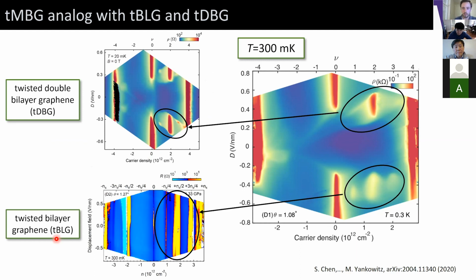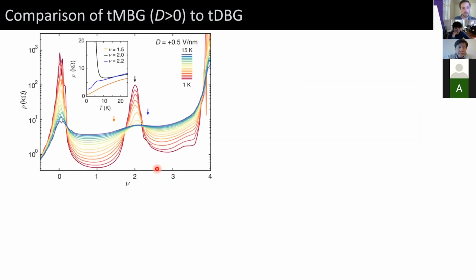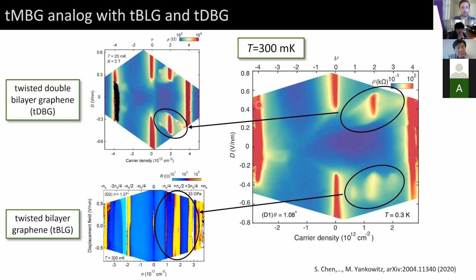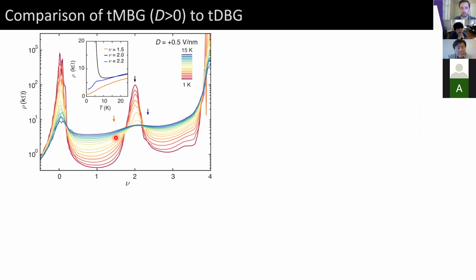So in the positive displacement field sign, we see this correlated insulating state surrounded by this extended halo-like region. And indeed, that looks quite a bit similar to what we see in twisted double bilayer graphene. And in contrast, on the negative displacement field side, we see these 3 roughly equivalent states at all quarter fillings of the bands. And that's reminiscent of what's happening in twisted bilayer graphene, where we have insulating states at each of the quarter fillings of the bands. Okay, so I'm going to start with the positive displacement field side and show you the temperature dependence for, I believe, 0.5 volts per nanometer, which is cutting through this correlated insulating state.